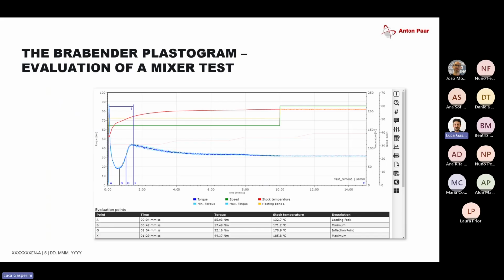And this whole fusion test is, let's say, an important test if you want to optimize the quality of your PVC dry blend, and if you want to see how you can process your PVC and what the processing window is. Will it degrade? How long can I keep my PVC inside the extruder before it can degrade?